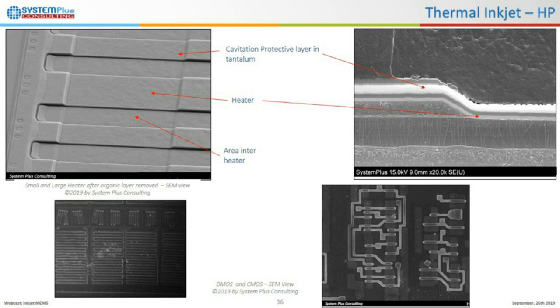It's complex because each time you heat the ink, you generate a shock, and you need to protect your circuit, the electronics close to the circuit, and the heater from the mechanical effect. For this, they use a very specific layer called the cavitation protection layer.